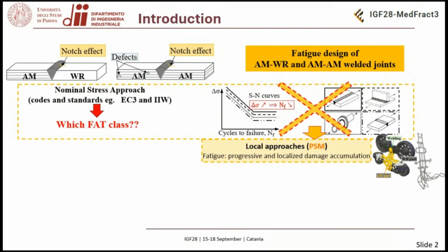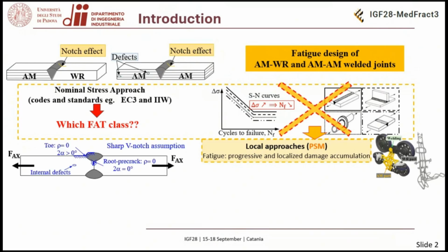The local approach that now I briefly show you, and that is the method that I apply also to reanalyze my fatigue data, is the peak stress method. The peak stress method is a method developed in Padua, which is based on the assumption that the weld toe of a welded joint can be assumed like a sharp V-notch.